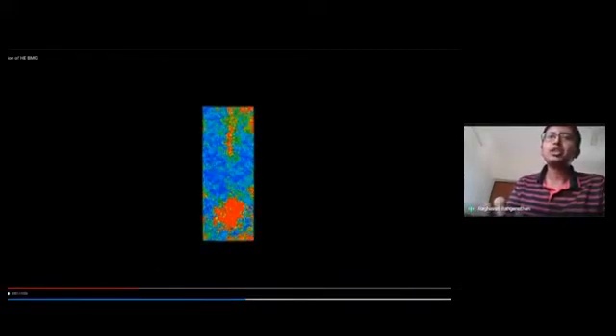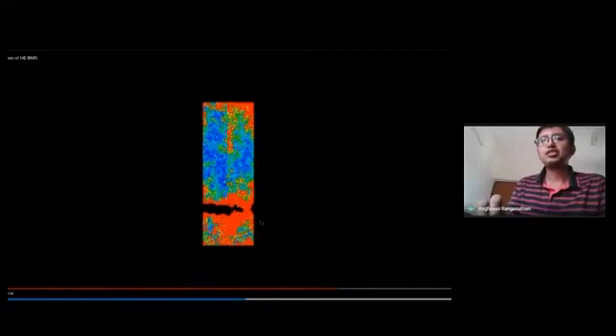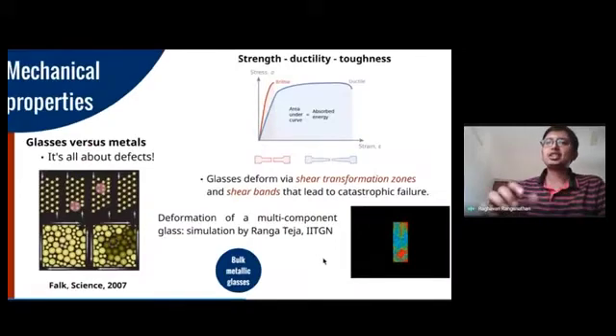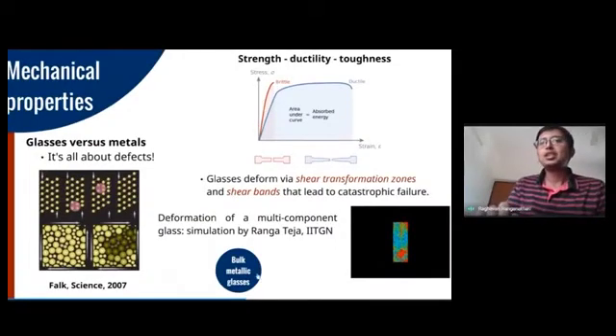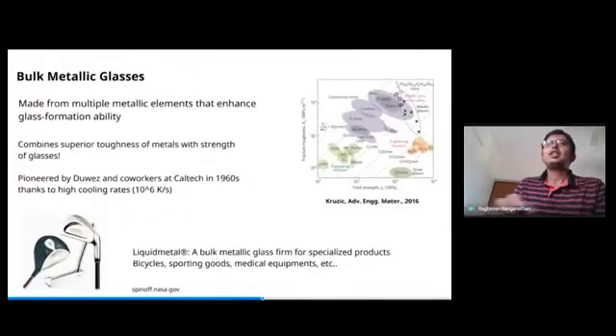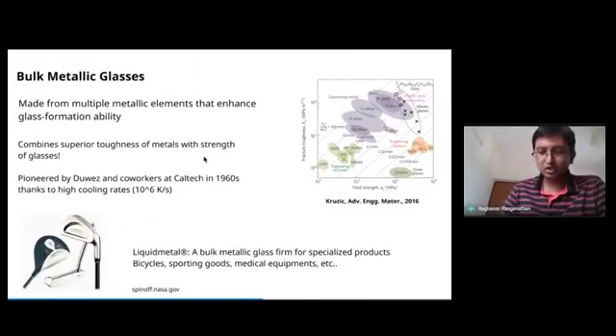So you can see that strain starts to get localized in some of these regions, and these are clear indicators of all these shear transformation zones that I just talked about. And as you progressively pull on the material, the shear transformation zone grows and eventually leads to a catastrophic failure. So that's the entire essence of deformation in glasses. So that was the traditional drawback of glasses, in that it cannot withstand a large amount of stress and